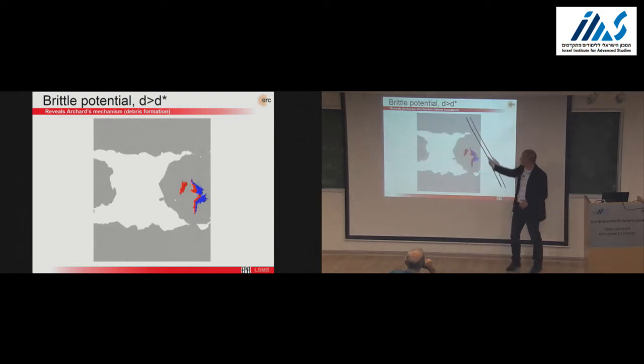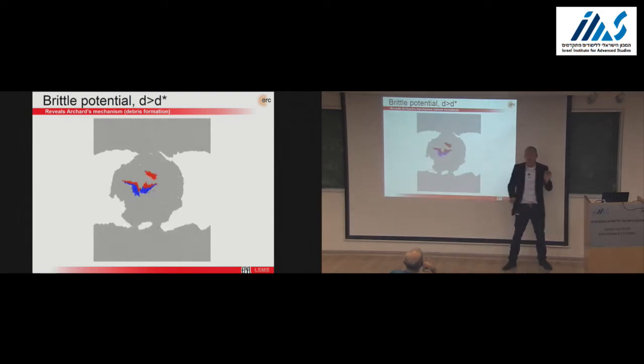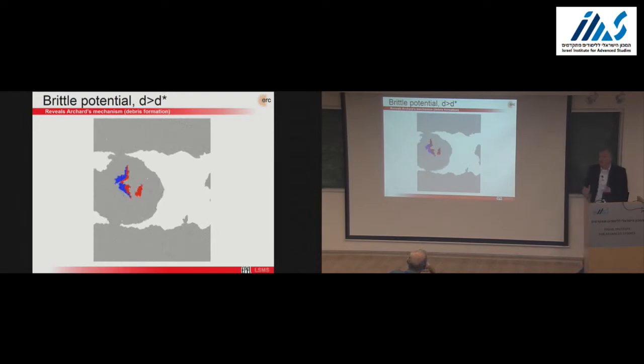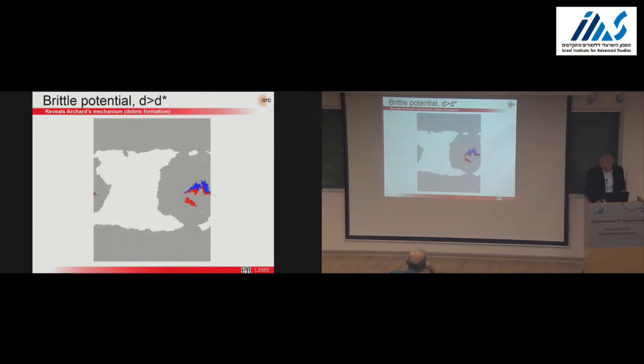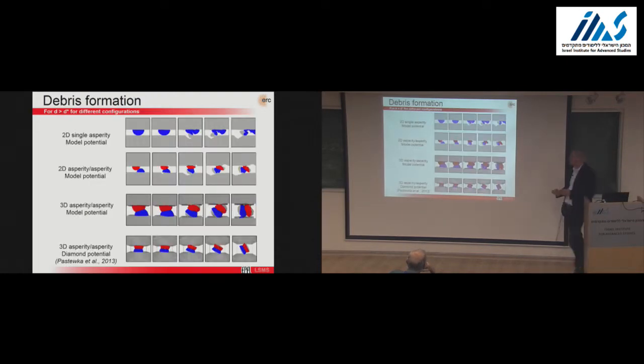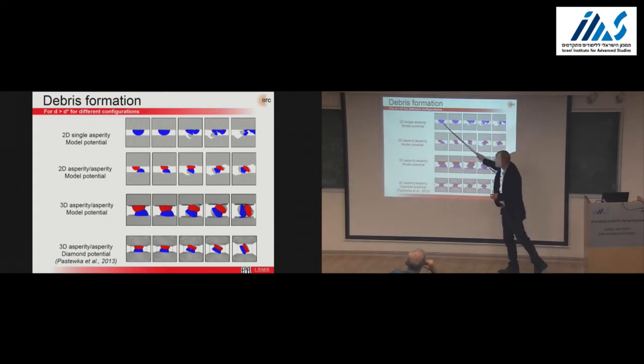So we have this transition at D star, and it's actually not an extremely sharp transition, but there's a transition that we repeatedly observe for single asperity sliding tests, 2 asperities in 2D, 3D asperities, those are much more expensive calculations, even including state-of-the-art diamond potentials, we also observe those things.